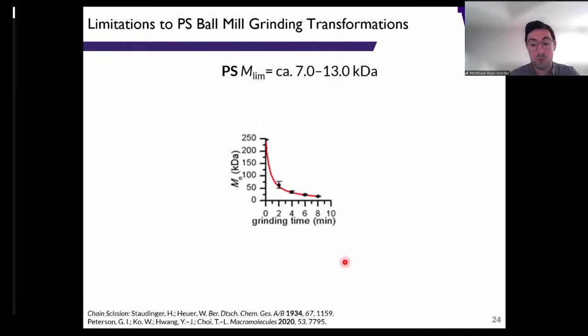Right, and this was shown recently by Peterson and Choi. Right, you can look at this high molecular weight polystyrene and just sticking it into the ball mill. We quickly evolve down to what's called the limiting molecular weight. Right, so this is where polystyrene will break down into really small oligomers on the order of about 10 kilodaltons or so. This happens in just about 10 minutes.